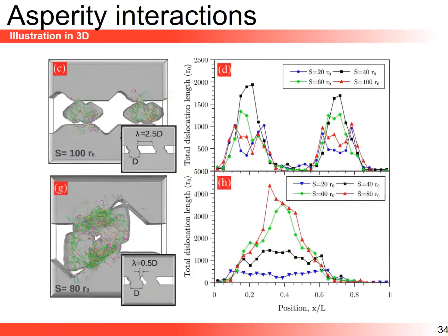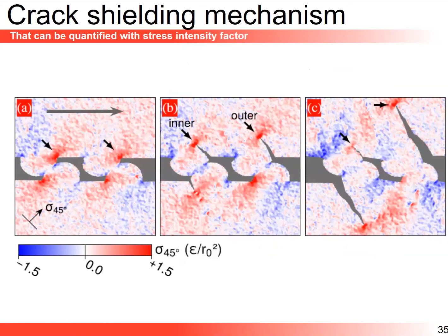Let me skip this, same illustration in 3D. And a mechanism that we have observed is a crack shielding mechanism, where at those two junctions, you're going to develop cracks at the corners of our junctions. You have a crack here, a second one there, a third one here. You're going to develop a fourth one here at the red regions with high tensile stresses. But this inner crack propagates a bit slower than the outer crack, and therefore is unloaded by this propagating outer crack. And this inner crack shuts down, right? It's healing itself. And therefore we get this one large debris when asperities are close by.